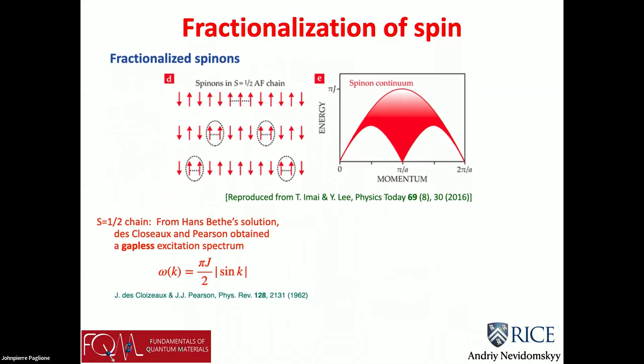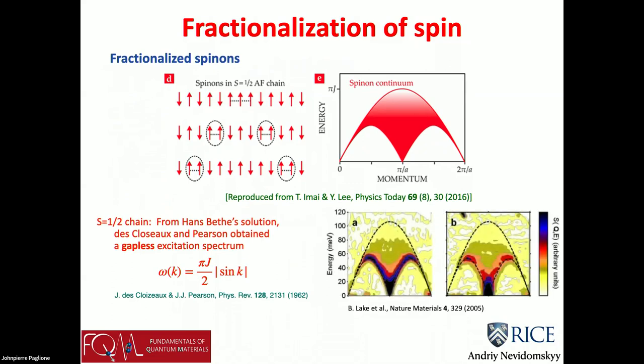Right. But now let's take that picture. It turns out that this can be shown rigorously in an analytical solution using the so-called Bethe ansatz. And then experimentally, Bella Lake and collaborators showed about 15 years ago that you actually see this continuum in quasi-one-dimensional materials that look like chains of atoms. I don't remember the compound, I apologize, I should have put it on. But this is the best example of spinons that we have. So if you have a one-dimensional chain of spin-half particles, they have this weird gapless excitation of spinons, and that's the best example of fractionalization.